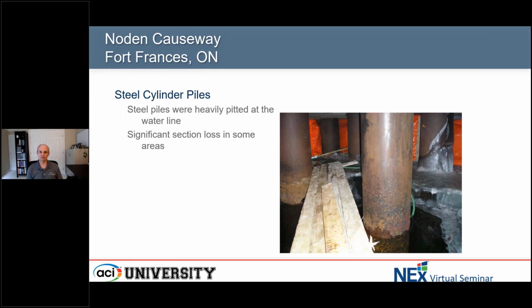There was quite a bit of damage to these steel piles that was really the result of microbial-induced corrosion. So there is an organism in the water that creates a corrosive environment for the steel, and that organism creates this environment that creates a lot of pitting corrosion on these steel piles. So you can kind of see that damage in the photo, but again, it doesn't really do it justice. There was quite a bit of pitting corrosion going on throughout all of the piles on this structure.